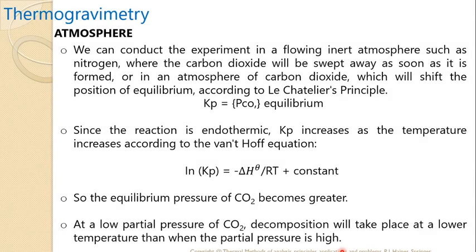We can conduct an experiment in a flowing inert atmosphere such as nitrogen, where carbon dioxide will be swept away as soon as it is formed, or in an atmosphere of carbon dioxide, which will shift the position of equilibrium according to Le Chatelier principle. Kp is equal to P_CO2 at equilibrium.